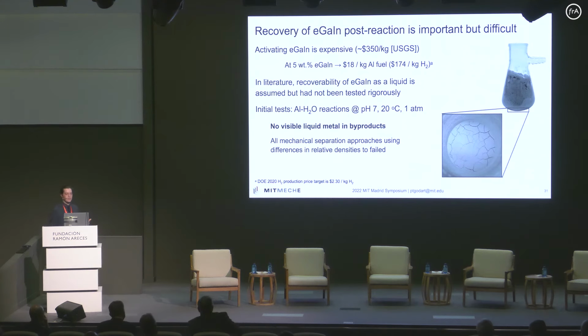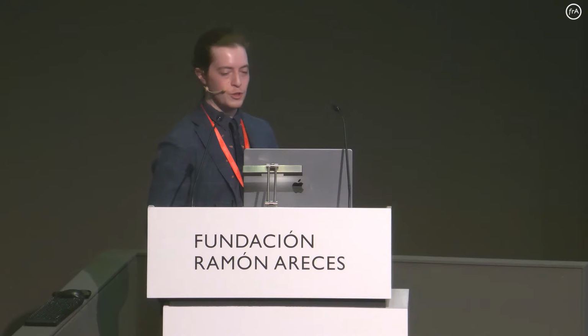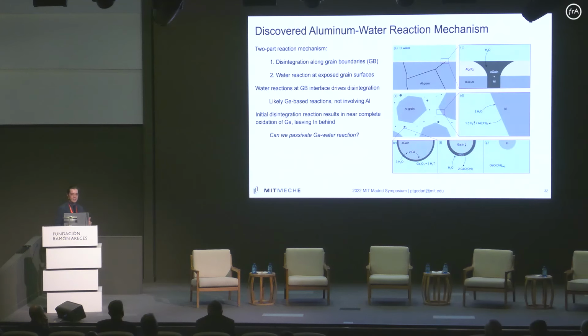And you can't simply recover it by mechanical means. And people thought maybe you could centrifuge it and it would sort of fall out. But we, of course, tried that, and we were not able to do that. So we had to dig a little bit deeper. And so what I ended up doing was coming up with a model for this aluminum water reaction. And informed by the videos and the SEM images that I showed you, we realized that this aluminum water reaction is happening in two parts.